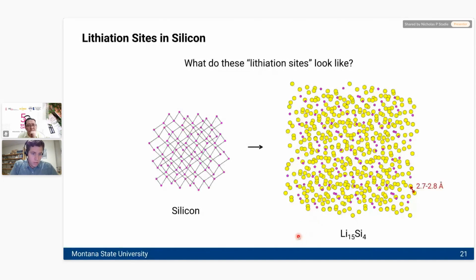So to give you some numbers on lithium distances here, I looked it up. These sites are somewhat more disordered and they're not as nicely symmetrical as they are in LiC6, but the closest distances are on the order of 2.7 to 2.8 angstroms, so smaller than, but just slightly below what it would be in metallic lithium. That is really a key difference between how silicon and graphite work. And so as a driving message today, silicon, yes, on paper looks great, but when you actually look at the mechanism of lithiation of silicon, you must be asking yourself, is that a sustainable lithiation reaction over and over and over again and back and forth in an electrochemical cell?